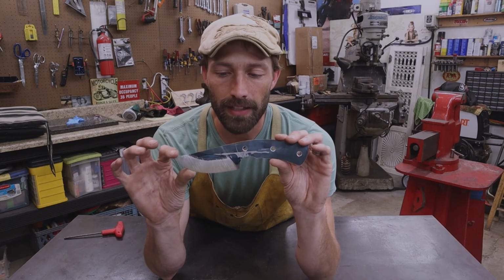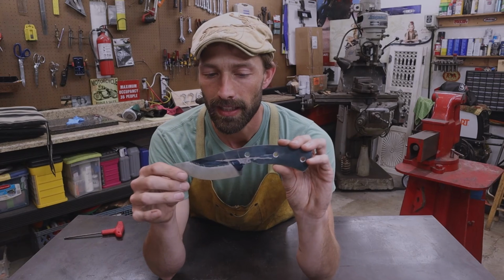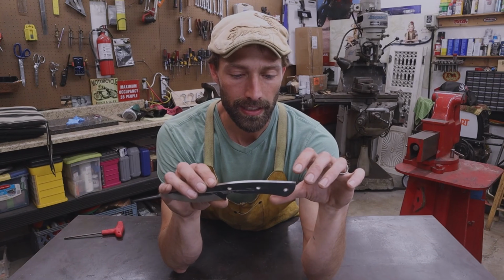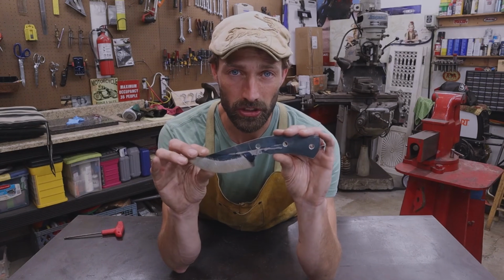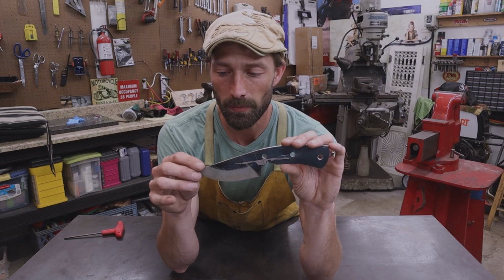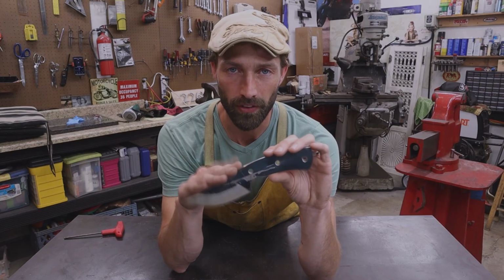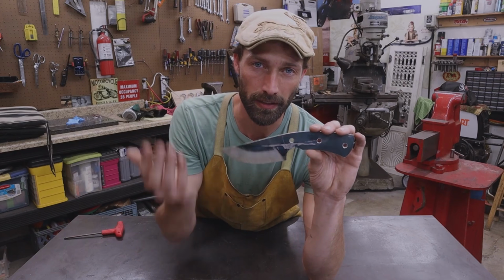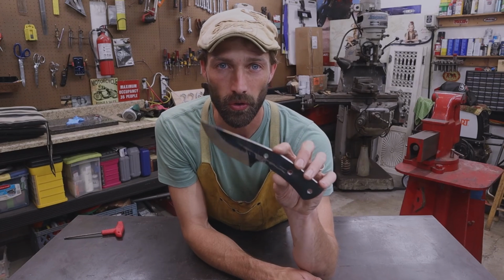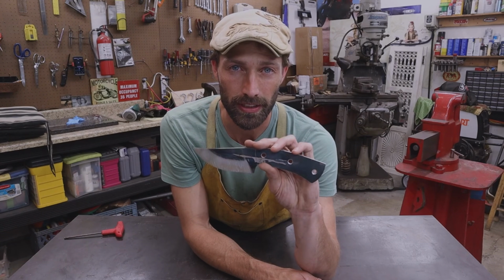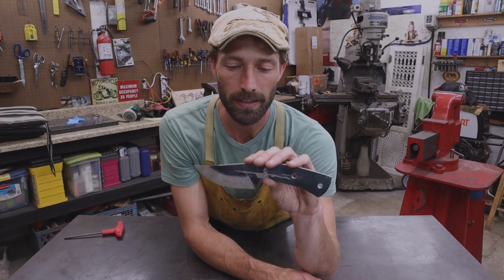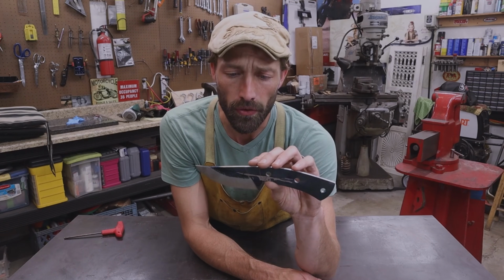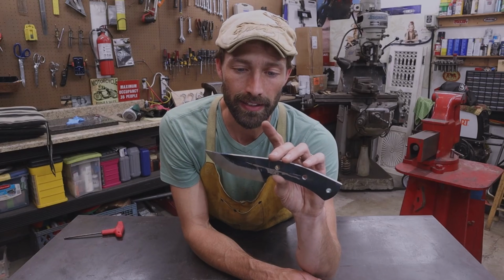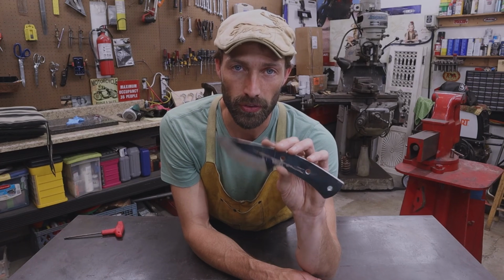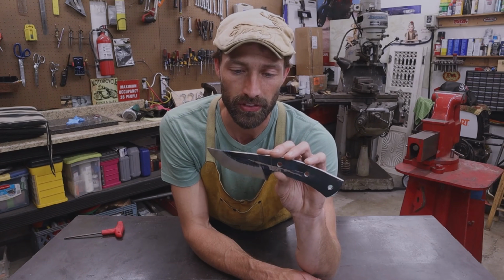You could heat treat 1095 a lot of different ways. We're gonna use a canola oil to quench this knife in. What we're gonna do to make that oil a little more adequate for quenching 1095 is we're gonna raise the temperature on the canola oil to about 125, 130 degrees before we use it. And that's gonna make it a little thinner viscosity, and it will be better for heat treating this 1095 steel.